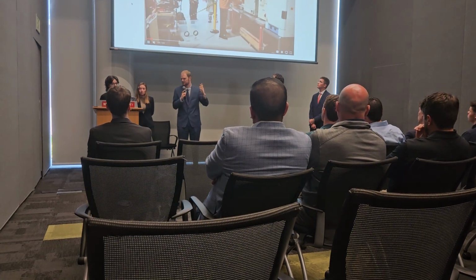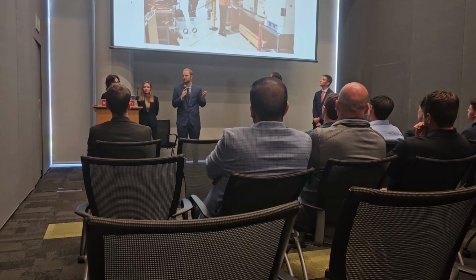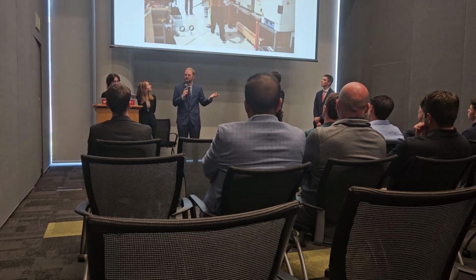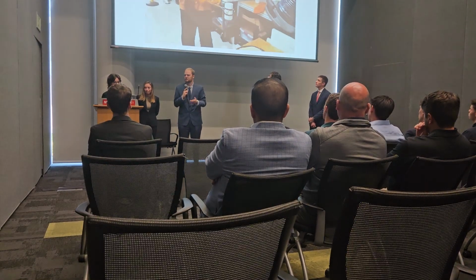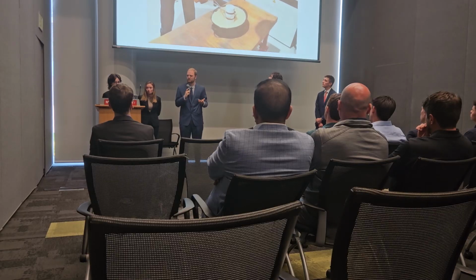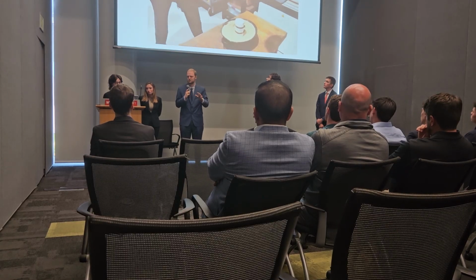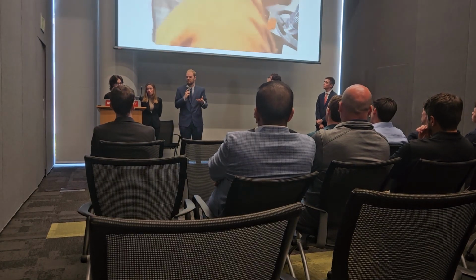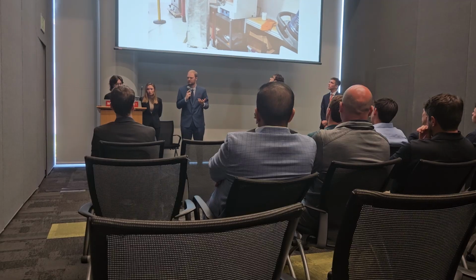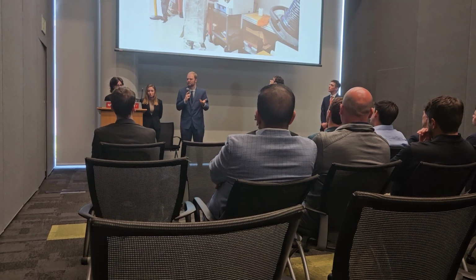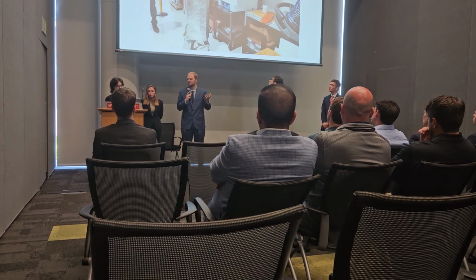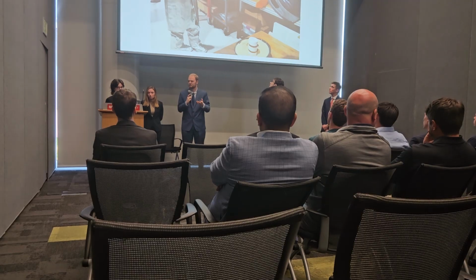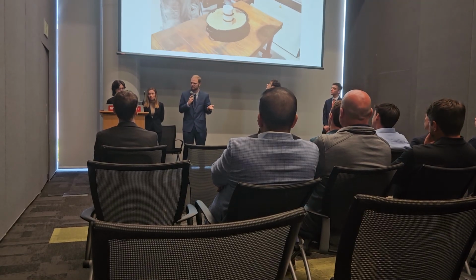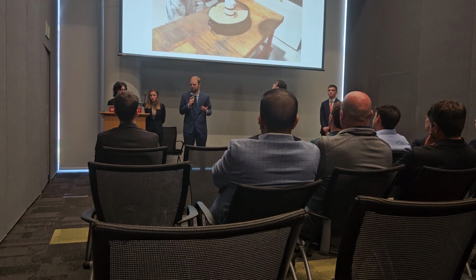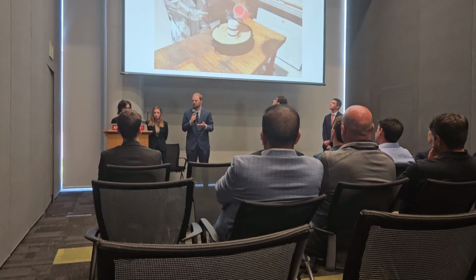As you can see, there is Justin. He is going to place the 450 or 500C preheated mold in our sand just to catch any material that would have fallen out, and also to disperse the heat from the melt. That is me. I am currently grabbing the crucible with the 900C aluminum 7075 and the nanoparticles, and we just pour it directly into our mold.